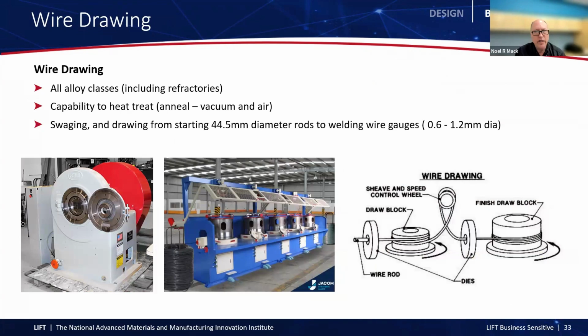On the swaging and wire drawing, we typically start with a roughly 45 millimeter diameter rod. We'll swage that down to roughly 1/2 inch and then run that through a traditional bull block to as small as 0.6 millimeter diameter wires. If we think of one rod that has been cast, and we can cast up to 24 rods at a time, one rod that is cast, if we draw that down to say 0.6 millimeter, that represents about a mile of wire. So through this capability, we can produce roughly 24 miles of wire from one batch through the melt cast process.